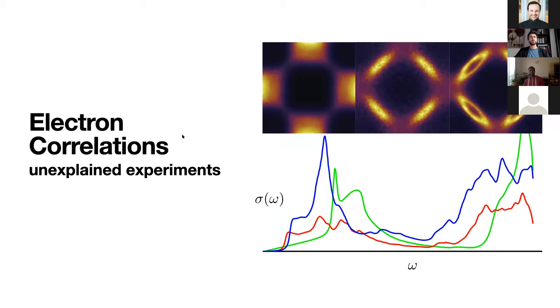The big problem with that is that for many of those materials, the correlations between the movement of electrons in one part of the material and the correlations with the movement of electrons in the other part of the materials are very challenging mathematical problems. If I think for example of some of the superconductors I was talking about, if you shine a laser through the material you will eject some electrons. If you map all the directions of those ejected electrons you can create a map of how the electrons were moving in the superconductor. With classical theories you're always expecting to find some pockets that look like this, but in very wild cases you will find blurry patches of electron disposition. This is not understood at the moment; these are results that are unexplained by the current theories.